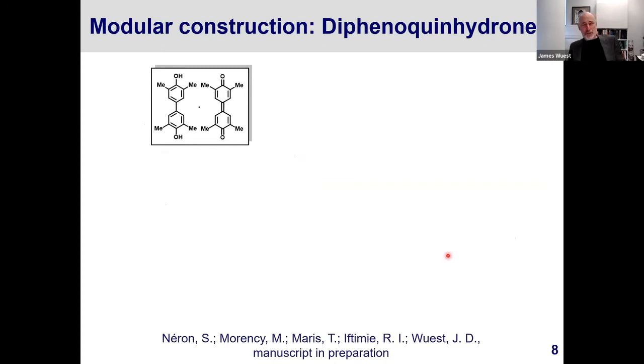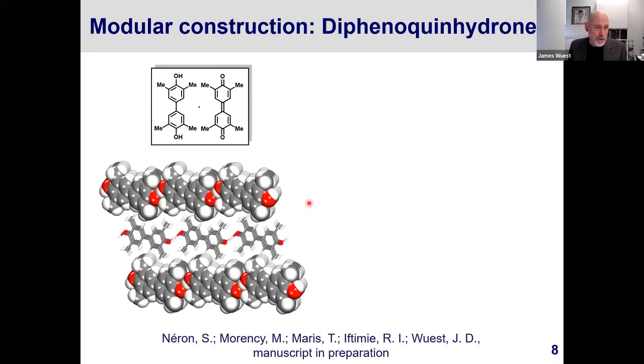Well, back to the subject of co-crystallization. So if you can co-crystallize hydroquinone and benzoquinone, well, what about co-crystallizing a diphenoquinone with a dihydroxybiphenyl? And this works perfectly well. It gives the same type of co-crystalline structure that we see in the classic quinhydrone motif. So you have here a dihydroxybiphenyl that is linked to a diphenoquinone, which is linked to a dihydroxybiphenyl to form a hydrogen bonded chain. The hydrogen bonded chains stack by charge transfer relationships to give the same type of layered structure that we see in the case of the simplest combination of hydroquinone and benzoquinone.